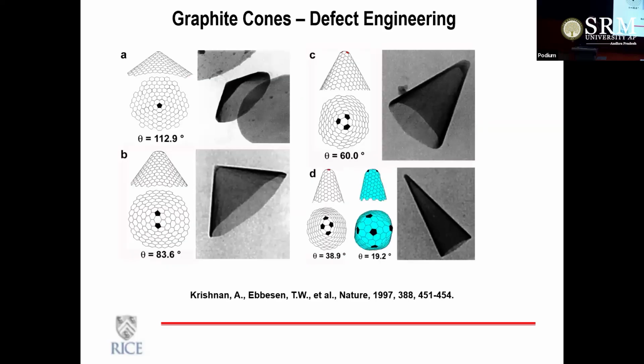Now, before I go to the final section, I also want to mention the impact of defects. Defects are everywhere. Thermodynamically, defects are stable. But defects are particularly interesting in graphitic structures. The whole nano-carbon revolution that I mentioned came about because defects get incorporated into the hexagonal graphitic network. That's why you can create fullerenes. You have topological defects. That's how you take a flat sheet of graphene and curve it into a ball. You need these 5-member defects.